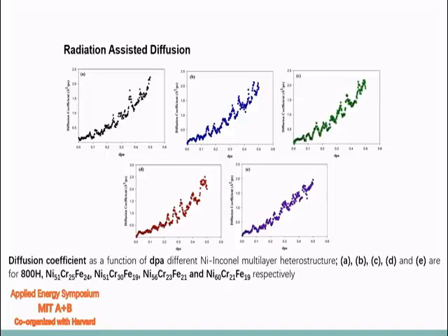The diffusion coefficient doesn't vary that much depending on the composition of the Inconel, but the nickel 56, chromium 23, iron 21 structure has a higher percentage of nickel and a higher percentage of chromium, so it has a little bit higher diffusion coefficient. Chromium has a very low migration barrier, so it diffuses faster and creates some defects, and in the presence of the defects, the migration barrier for nickel also gets lower. So the nickel atoms also start to diffuse faster and create some defects, and that accelerates the diffusion. That's why we get the faster diffusion for the nickel 56, chromium 23, iron 21 structure.